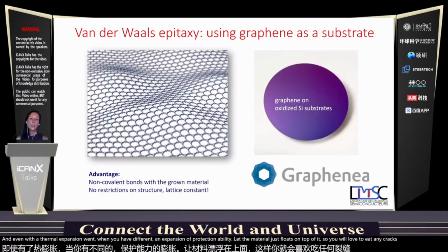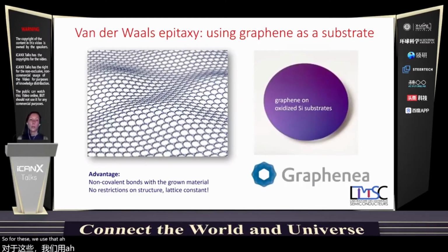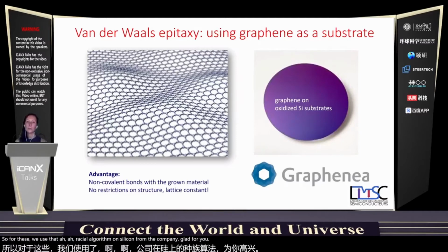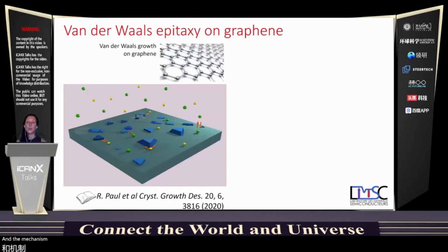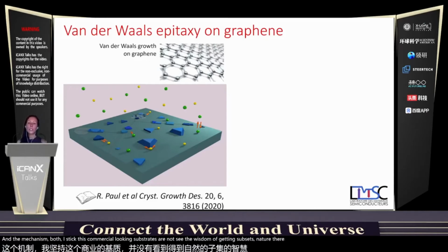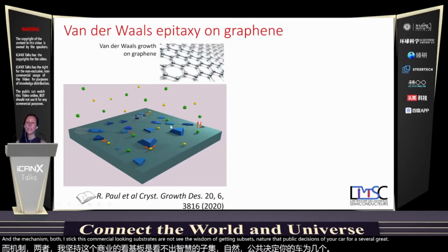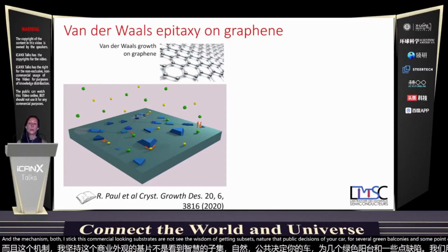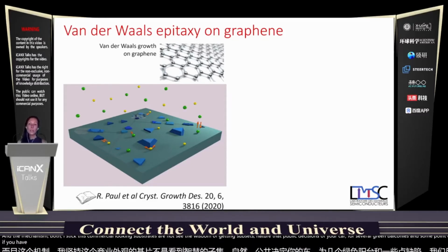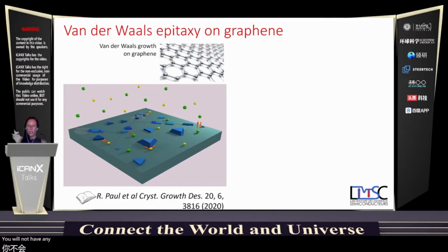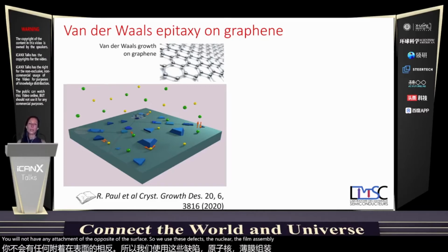So for this, we used commercial graphene on silicon from the company Graphenea. And the mechanism goes like this. These commercial graphene substrates are not single crystalline graphene substrates. They are polycrystalline, so you have several grain boundaries and some point defects also. And we use this as a way to nucleate the material. Because if you have pure graphene, you would not have any attachment of the atoms that come to the surface. So we use these defects to nucleate the film and start growing laterally.